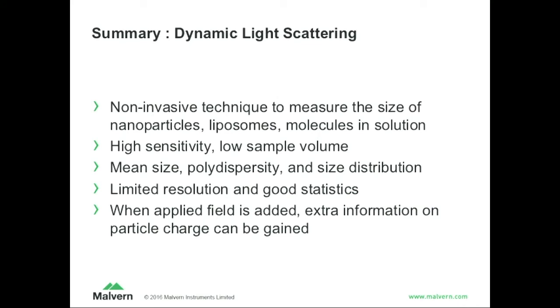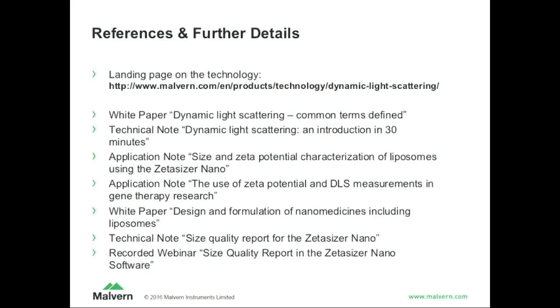So in summary, particularly about dynamic light scattering: it's a non-invasive technique to measure the size of nanoparticles, liposomes, molecules in solution. High sensitivity, low sample volume needed. You get out the mean size and the polydispersity, and in many cases even the size distribution. While we do have maybe limited resolution, we have very good statistics. And when you apply an electric field extra, you can get extra information about the charge of your particles. If you have any questions, I'd be happy to answer them.